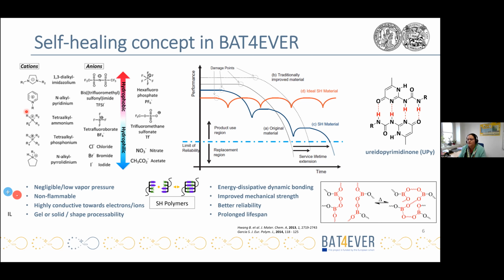Besides the kind of the bonds, also the mobility of the polymer chains plays a role. So if the polymer backbone can move faster or easier, then also the supramolecular bonds can come to each other again more easily and heal the material. So the interplay between the self-healing groups and the polymer backbone itself at the end gives this final self-healing temperature.